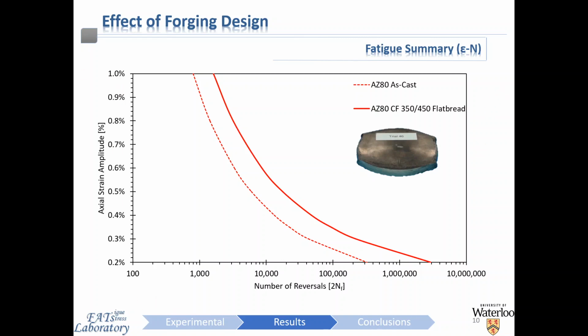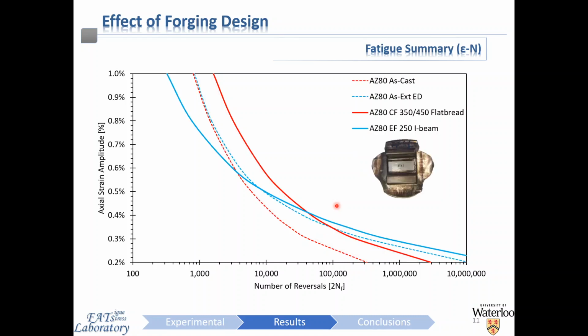Here we can see a dramatic improvement in the fatigue performance of the as cast material once forged in a simple upsetting technique to produce these types of flat forgings here that do not restrict the material flow in either direction. So this is a substantial increase in material properties that's typical when forging cast varieties, as I previously discussed, of magnesium, which the benefit basically is coming from the refined equiaxed microstructure, which is resulting from the thermomechanical processing.